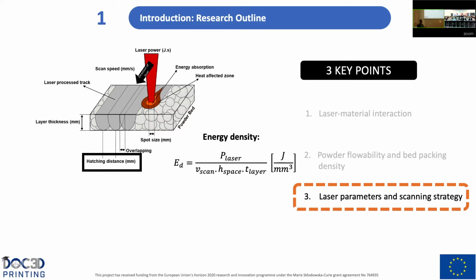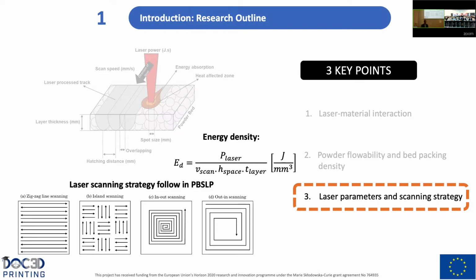Here we need to assure that we don't have a very big distance, to avoid regions without treatment, and on the other hand, that we don't have a lot of overlapping. Otherwise, we could have a lot of heating and some decomposition. And finally, of course, the laser scanning strategy followed in the process, because they determine the distribution of the energy density, and as we will see, it will have a very important role in the optimization of the process.